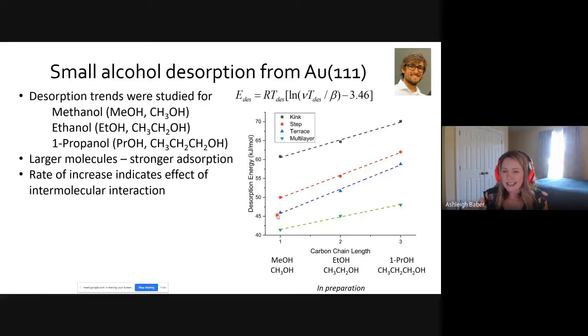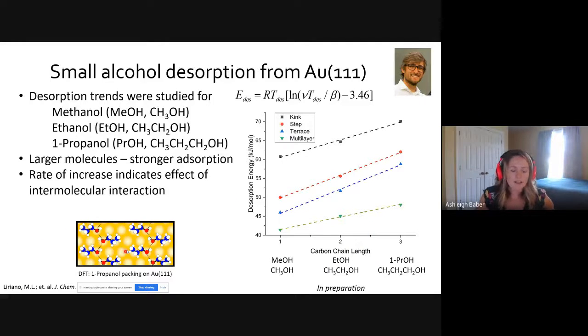But one interesting thing here is that if you look at the terrace trend for just a moment, you can see that as we go from methanol to ethanol to 1-propanol, there is this increase. But the slope of this line is not the same as the slope of the kink site, indicating that the rate of the increase is different for these two different surface features, which we are relating back to intermolecular interactions. So I am going to bring up here a DFT figure from one of Charlie Sykes' papers recently.